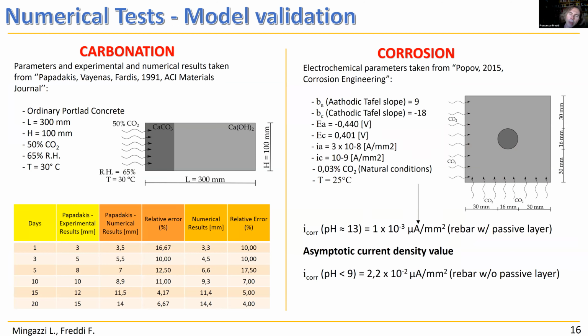First of all, we try to validate the carbonation and corrosion phenomena that we are trying to describe. So we just compare our reaction diffusion solution with some experimental results and other numerical models. And we just compare the depth of the carbonation front. And we can see that, especially with the experimental data, we are not so far from those results. Obviously, we are just comparing the carbonation layer depth.